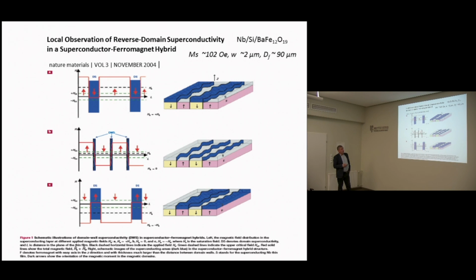And the idea is the following. Let's consider the first case where the external magnetic field is 0. According to the Aladyshkin model, the position of the order parameter will be situated where the compensation effect is the largest. It means here it is located at the Bloch wall. If we apply a magnetic field, for example in the opposite direction, then superconductivity of this area will extend from the domain walls up to the domain part which has the opposite magnetic moment. So this is the idea of the experiment.